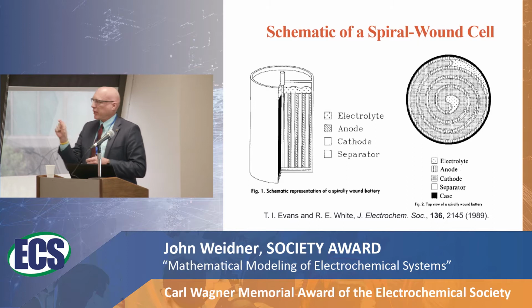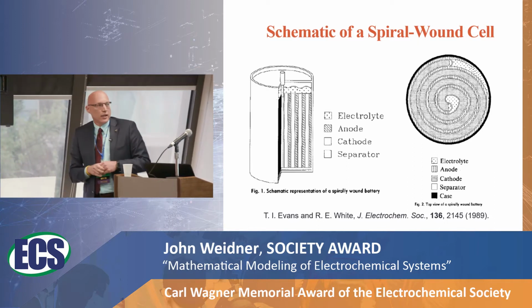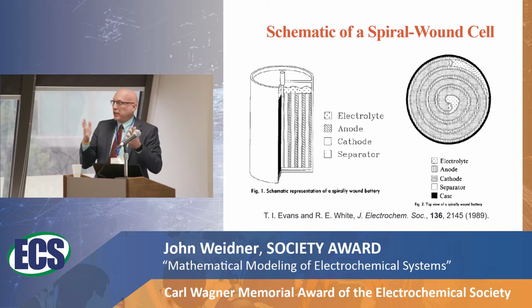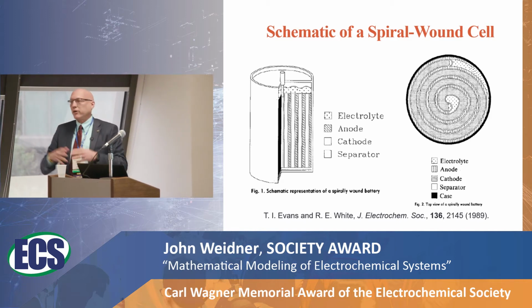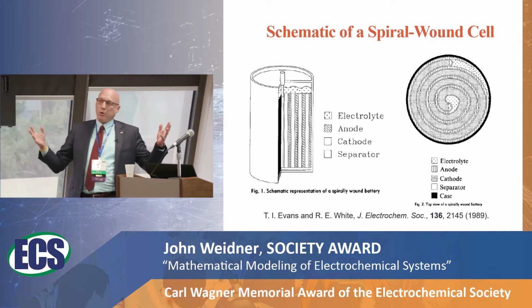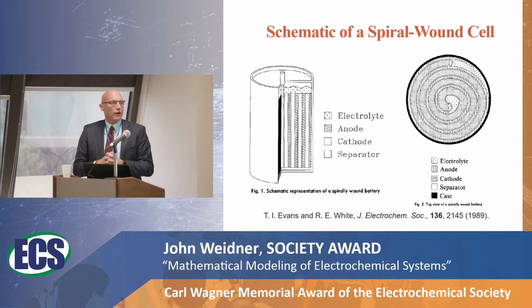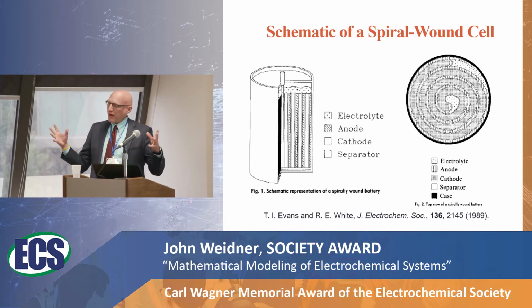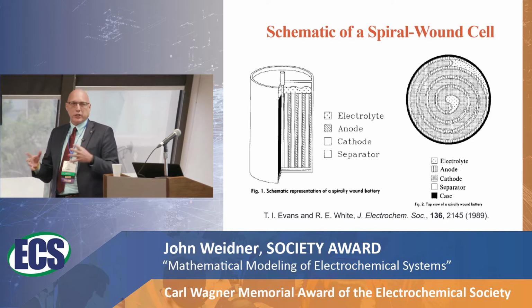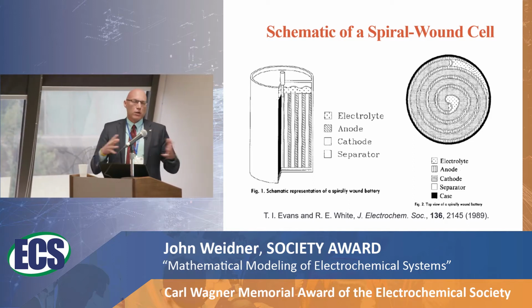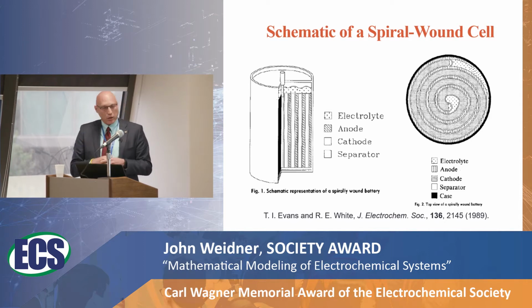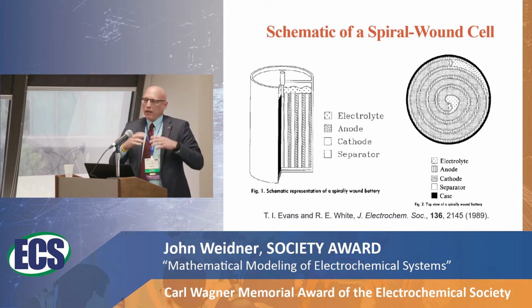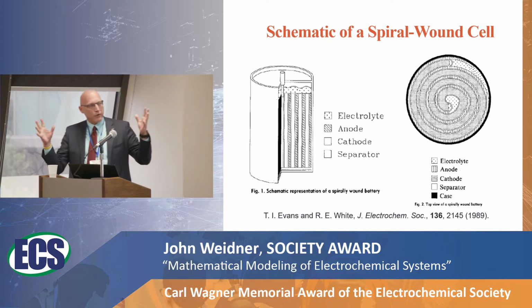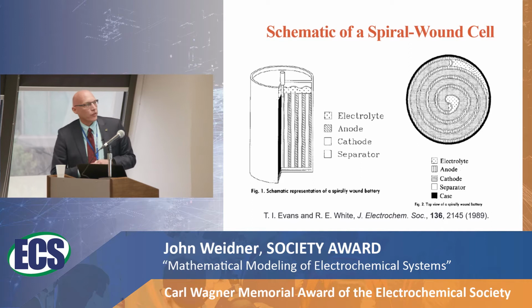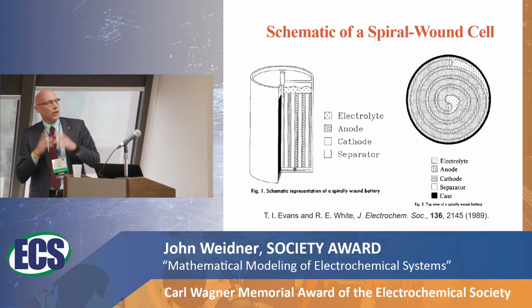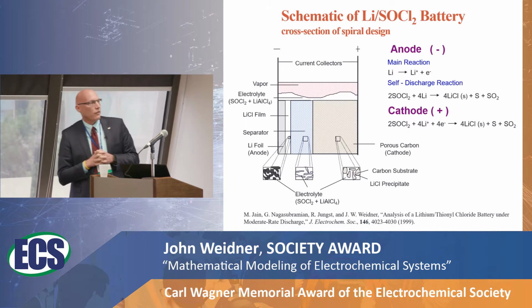So in here, the electrochemistry is actually occurring over a fairly small distance, more on the tens or hundreds of microns, where this battery is maybe a few centimeters, and if you put it in a cell pack or inside of an electric vehicle, it's even much bigger than that. So the thermal effects tend to be on very different scales than the electrochemistry, and marrying the thermal and electrochemical effects can be quite challenging. And so we worked on that as well. But again, always remembering that we're looking at some kind of large battery system, we model a single cell, and here's an example, and this is a lithium thionyl chloride system.